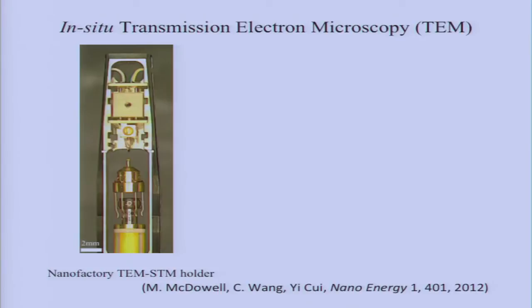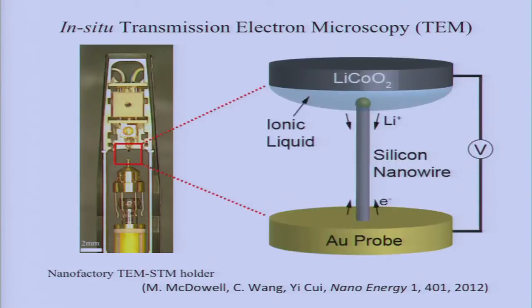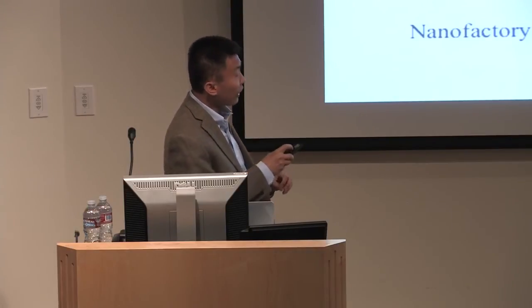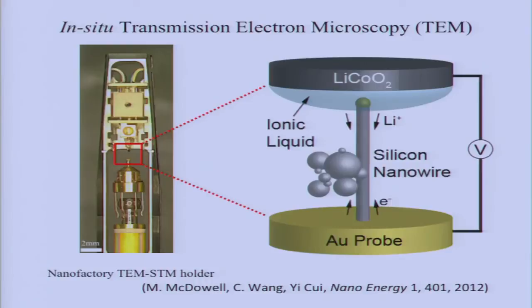Let me also show you the parallel development of new tools of in situ transmission electron microscopy happening on campus. We have a holder right now on Stanford campus to measure single-nanowire batteries. This is a holder with piezoelectric control. You can move your sample in and out, left and right, up and down. This is a lithium cobalt oxide cathode with an ionic liquid electrolyte that has very low vapor pressure. You put it into the high vacuum condition of a TEM chamber, and they survive. You apply a voltage driving the electrons, lithium diffuses, and lithium and electron neutralize and insert into the crystal of silicon. You can use this technique to see individual particle lithium reaction processes as well.